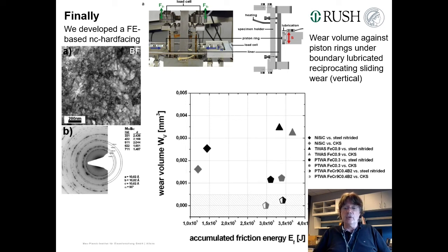This is the material that I developed within that project, because I did a lot in the early 1980s with iron, carbon, chromium, boron alloys in order to use borides instead of carbides for wear resistance. And certainly you do something which is close to what people did in order to generate metallic glasses. I never wanted to generate something which is amorphous, but it's very easy if you play around with chrome and carbon and boron to generate something which is per se nanocrystalline. So this stuff was very nice because industry said with respect to the frictional energy, that's absolutely okay. We accept it, and your wear rate is so small. This is really good stuff.